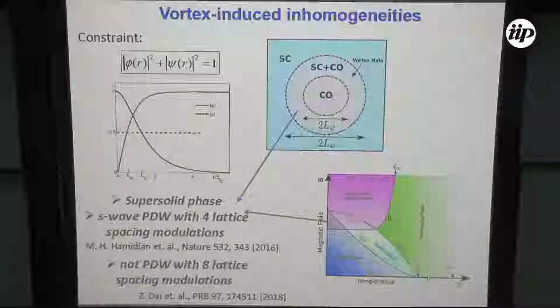So till now, I have not talked about any vortex-induced inhomogeneity. So if I look inside the vortex, as I said earlier, the superconducting order parameter will be suppressed inside the vortex. At the center, it would be 0. Now remember, we have a constraint on the two. So as a result, when one order parameter is 0, we actually enhance the other order parameter, which is the charge order, because of this constraint, which we also saw in STM measurements.